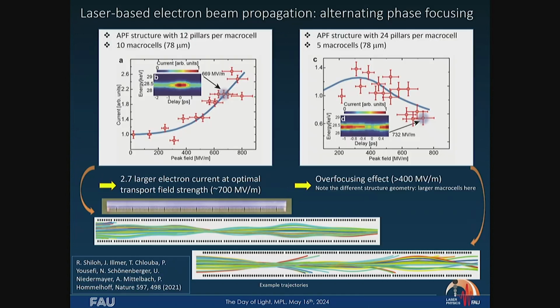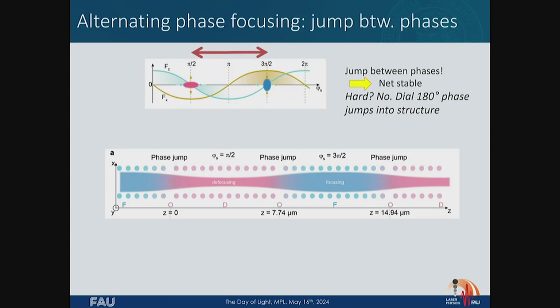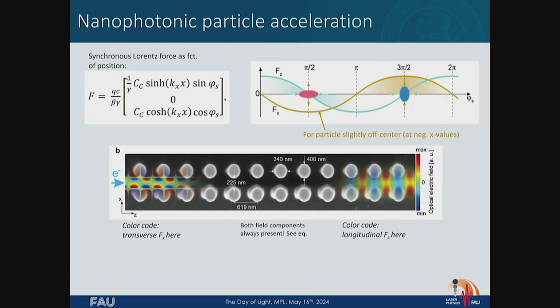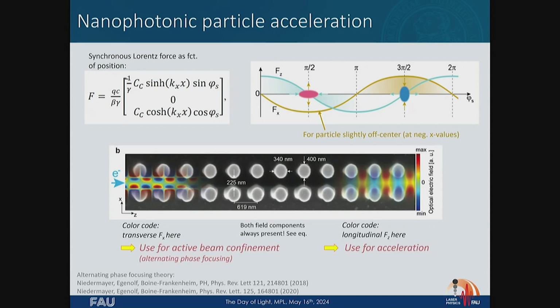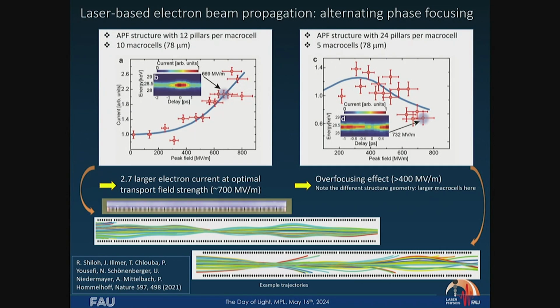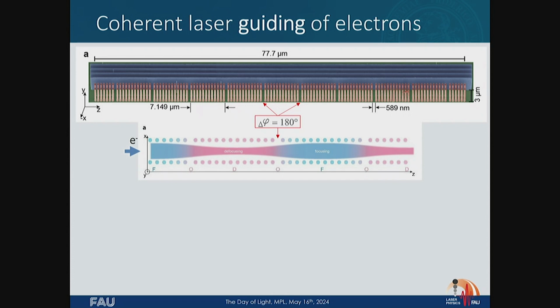When you get the top view, when you show them this one here, hold on, where is it? This one, so yeah, sure, we can do that, no problem. Then you show them the side view, and then everybody's asking you, so this one here, for example, ooh, that's pretty high, that's 2 to 3 microns high, gaps only 200 nanometers, the famous aspect ratio, or pillar diameter, roughly 200 nanometers, aspect ratio more than 10 to 1, that's tough.